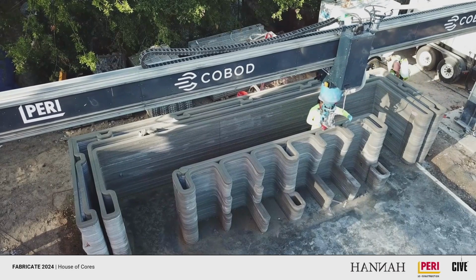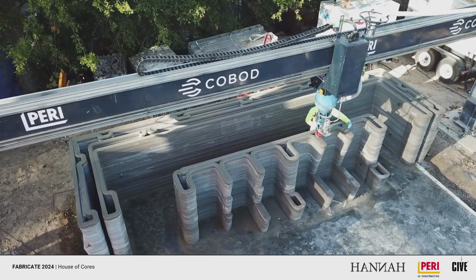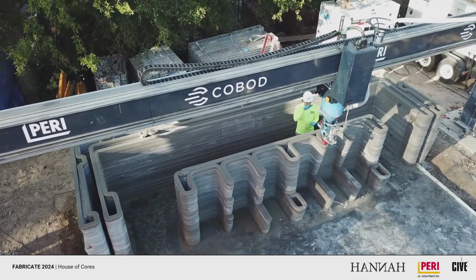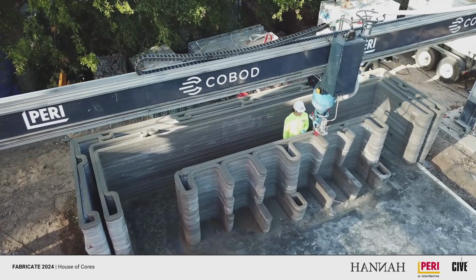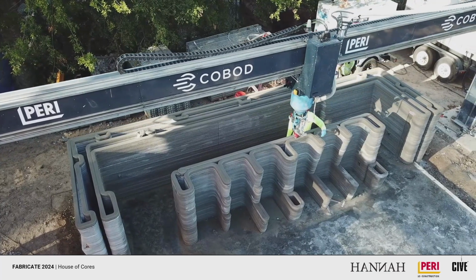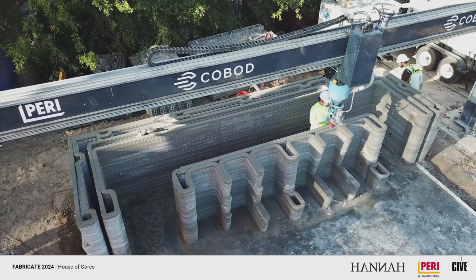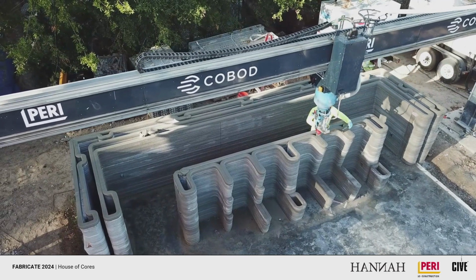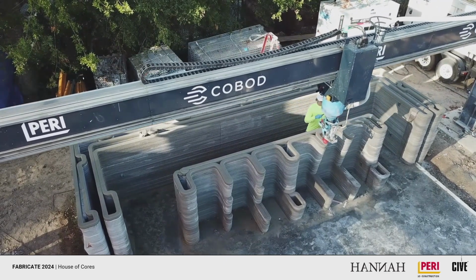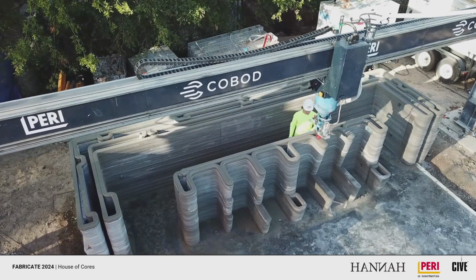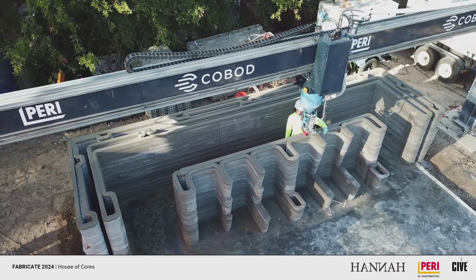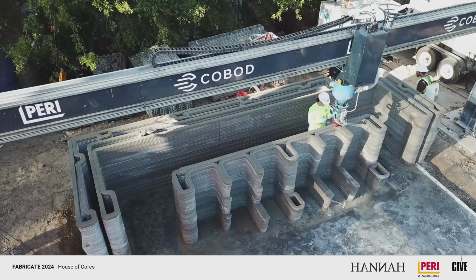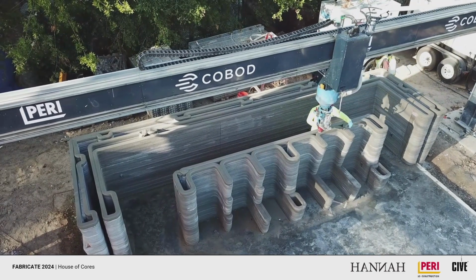And so the printing process is familiar to most here in this audience. It is, as we know, a delicate balance of rheological parameters, material compositions, printing speeds, layer times, flow rates, and environmental factors such as the blistering heat in Houston, Texas, which in one summer, I believe, ranged from 38 degrees Celsius to 42 degrees Celsius.